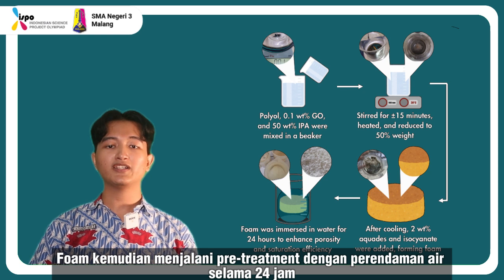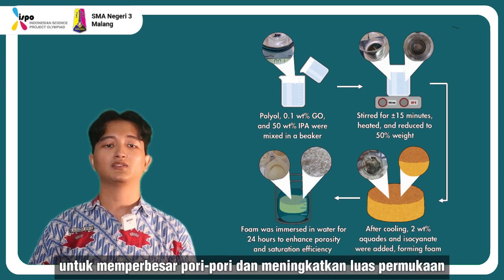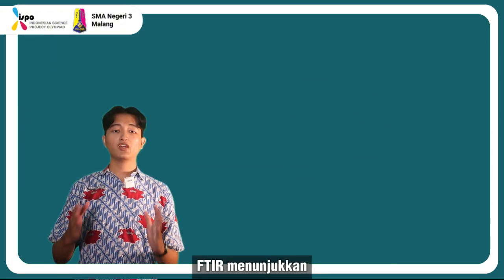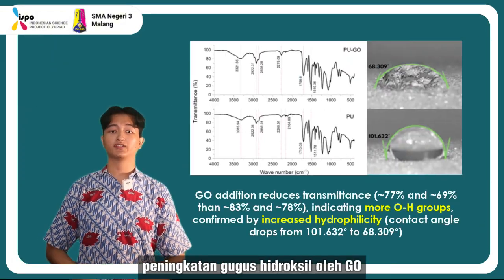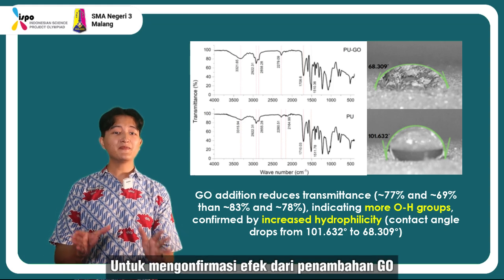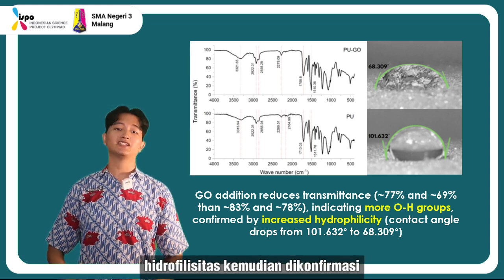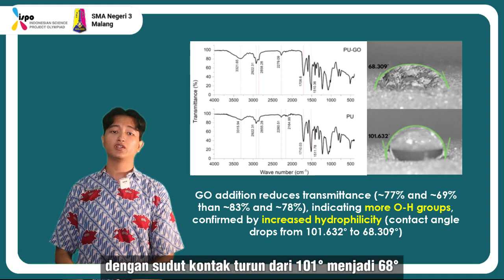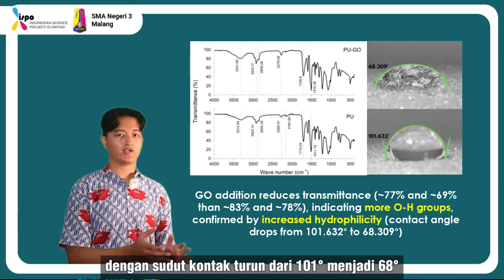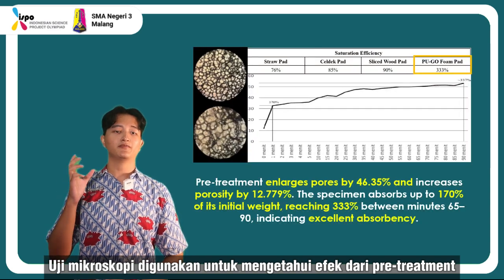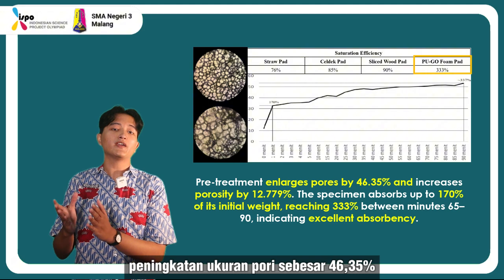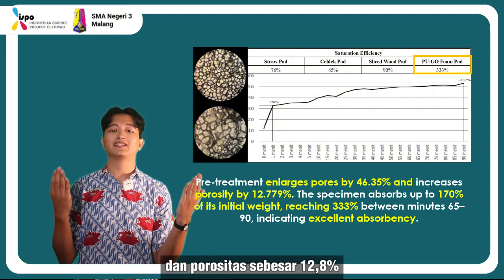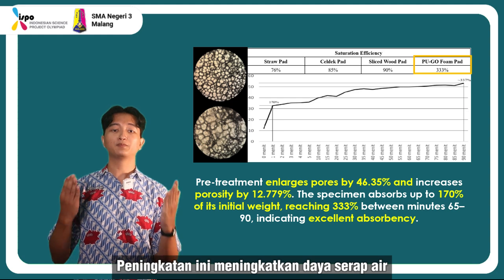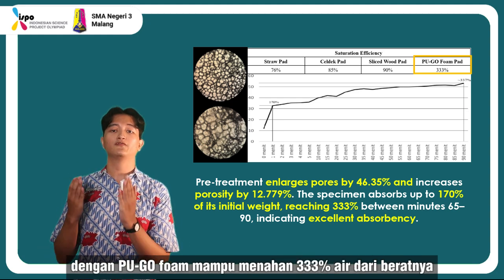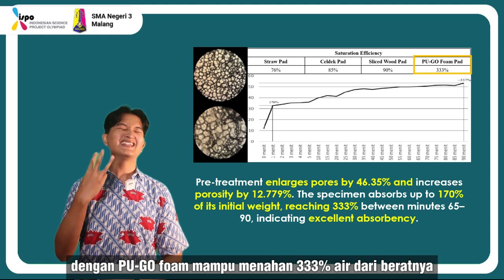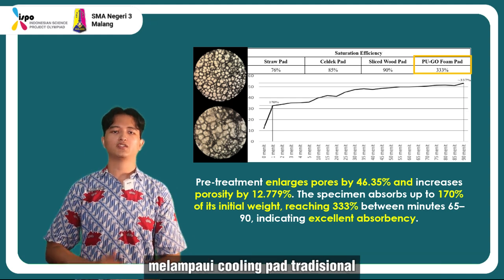The foam then underwent pre-treatment procedure with 24-hour water immersion to enlarge pores and increase surface area. It's shown that FTIR confirms GO increased hydroxyl groups, enhancing foam hydrophilicity. The hydrophilicity is then confirmed via contact angle analysis that shows a reduction from 101 degrees to 68 degrees. Microscopy test was done to see the effects of pre-treatment. It revealed a 46.35% increase in pore size and 12.8% increase in porosity. These improvements boosted water absorption, with polyurethane graphene oxide foam, or PUGO foam, retaining 333% of its weight, outperforming traditional cooling pads.